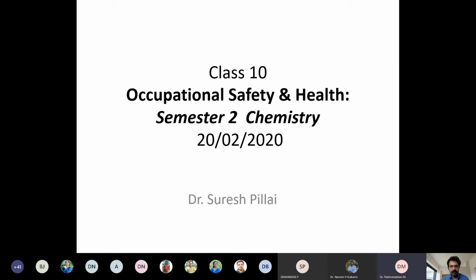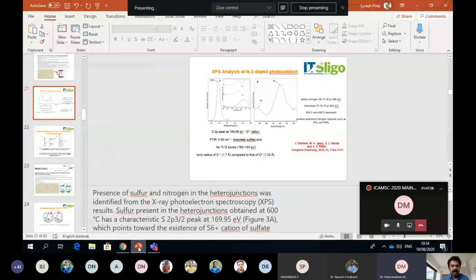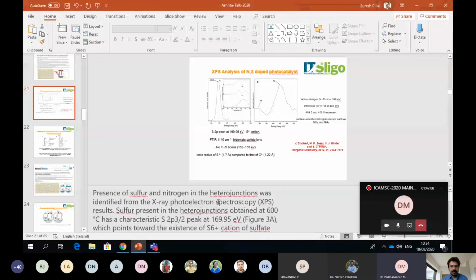Does it bring down the band gap? You have tried, probably. Yeah, it will reduce the band gap, of course. How much is the nitrogen content? Is it approximately maybe 1%? Oh no, less than 1%. It's 0.05 in some cases.